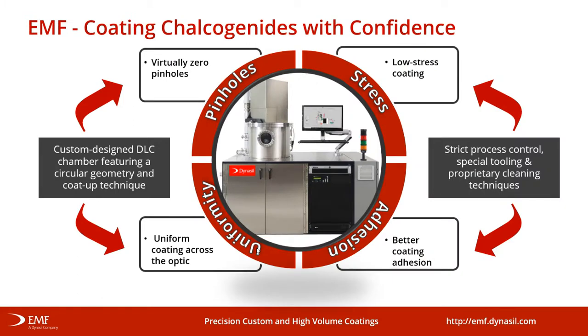So with our custom design DLC, we have virtually no pinholes, and our circular geometry and coating up technique increase the uniformity of the coating throughout the entire optic. In terms of stress and adhesion, we have strict process control, special tooling that's designed specifically for our chamber, and a proprietary cleaning technique that leads to overall better performance of the coating.